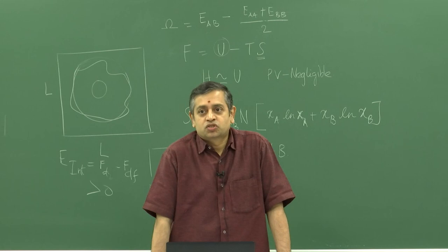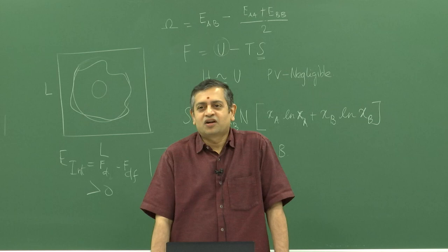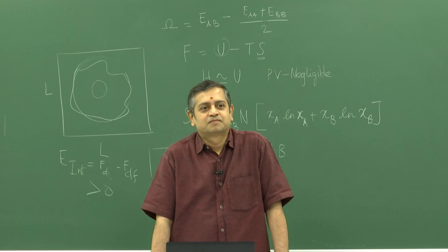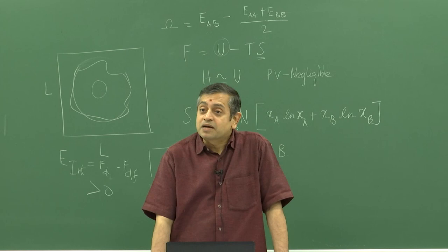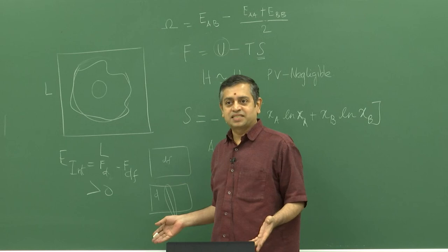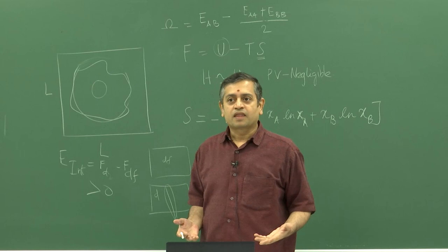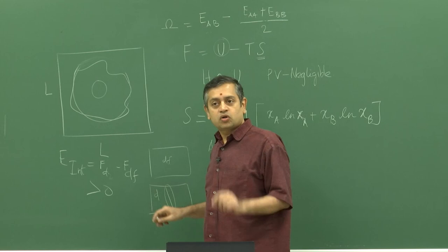If you truly look at the entropy arguments, no, except for point defects, I do not think, maybe in some cases dislocations. The rest of them you will not see as equilibrium defects. Strictly speaking, they should not be preferred. So let us assume that it is not excess, let us assume that it is negative, then what will happen? The system will become unstable, it will undergo a phase transformation. Maybe the stacking fault energy in some system you measure as negative, that means the system would prefer HCP instead of being FCC, right? Which means the defect will form spontaneously in your system, which means the system will be full of defects. Probably that full of defect state is something else, not the reference that you are considering.